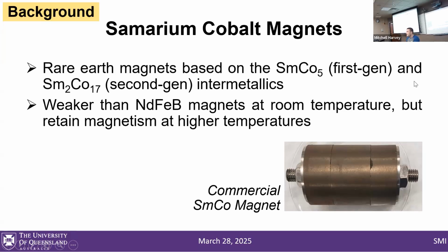And why we care about samarium cobalt is because even though it's weaker than neodymium iron boron magnets at room temperature, it has a lower reversible temperature coefficient. So all magnets lose magnetic field strength as temperature increases. And depending on the material, they decrease more or less as a function of temperature. So samarium cobalt loses less magnetism with temperature.